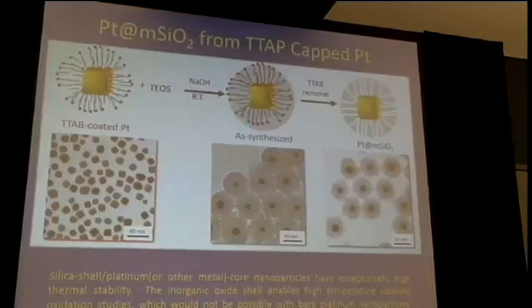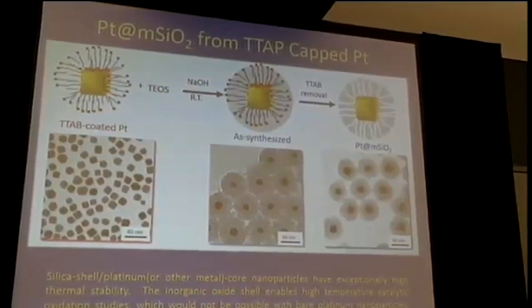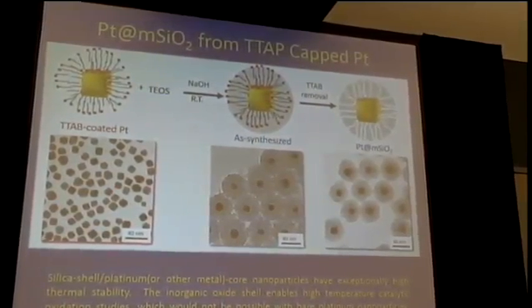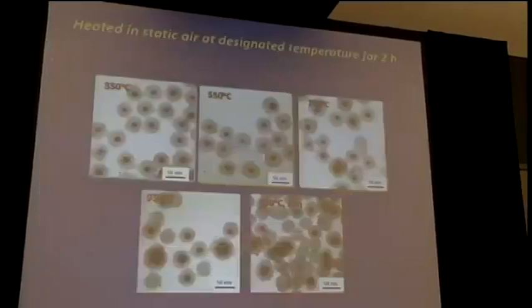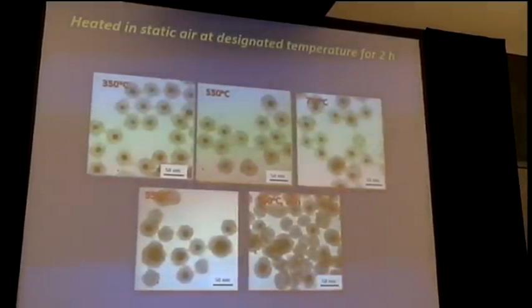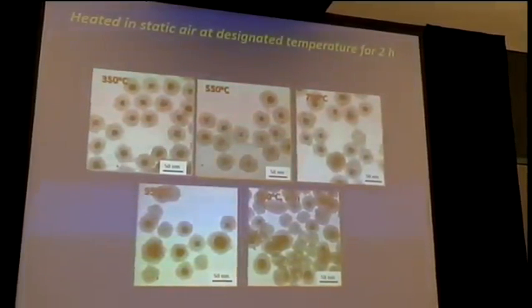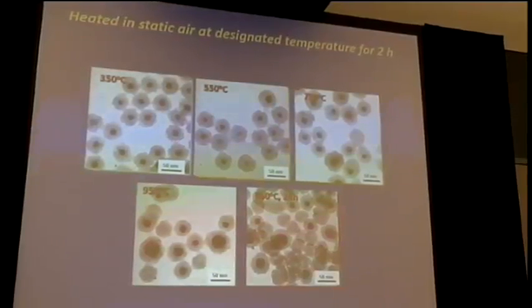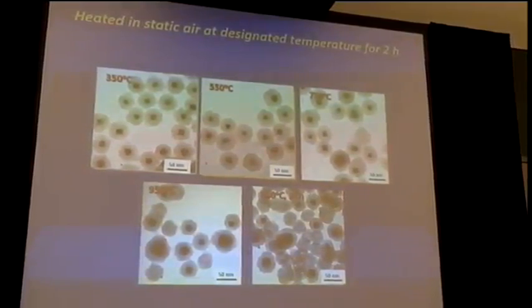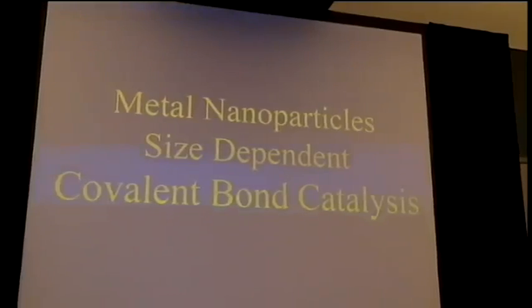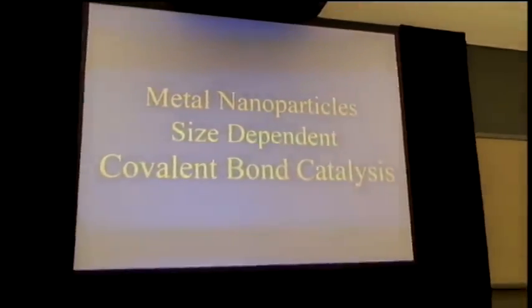And so when you want to do combustion chemistry, this is a problem. However, if you have a silica, mesoporous silica coating or alumina coating, then what you find is that you can go to 900 centigrade before these particles melt. It's still not the bulk melting point, but in fact you can do combustion catalysis around 900 centigrade or so. Now, let's just talk no acid base, just look at metal nanoparticles, covalent bond catalysis. And this is the final conclusion. The size and shape controls both catalytic reaction rates and selectivities.